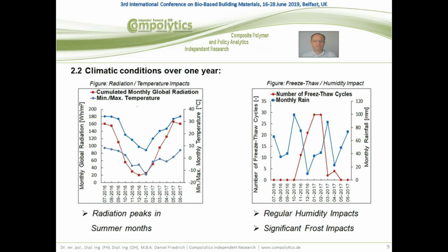This was the weathering conditioned over 1 year, which was a change in the monthly global radiation. As can be seen in the winter month, this went down massively but had the peaks in the summer month, and also the minimal and maximal temperatures varied over the year. And also in terms of the lows and the highest temperature, we can see that we had indeed freeze-thaw cycles over the year, which occurred mainly in the winter month, and also the monthly rain varied over the year but did not make a substantial difference between winter and summer month.